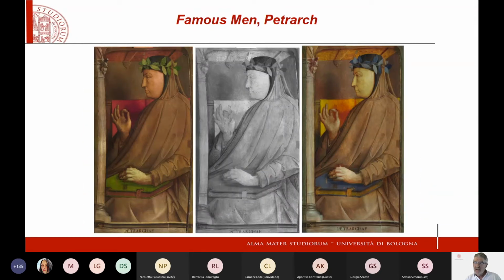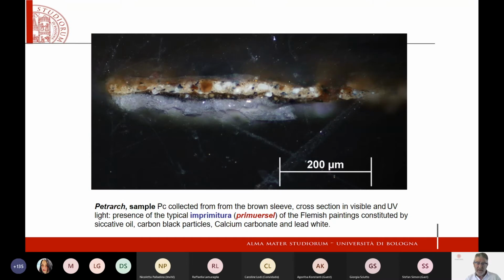But other than this, all these non-invasive techniques allow us to better understand from where to eventually take the sample in order to understand whether, stratigraphically and from the material point of view, there were some features that were typical of Flemish painting and that were not present at that time in the Italian painting technique. And this was the case of this very thin priming layer that was applied on top of the preparatory layer. This priming layer is typical of Flemish painting and is constituted by siccative oil, carbon black particles, calcium carbonate, and lead white, which is absolutely different from the typical priming layer that probably you all know was used in the